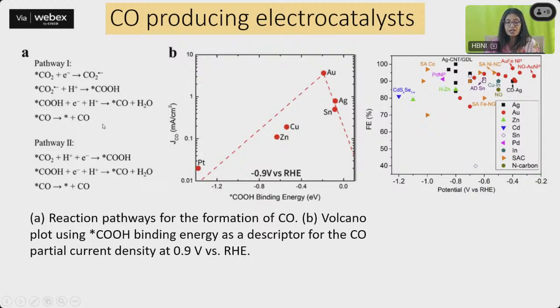Again over here, if you see the process, you are having the metal surface and you are seeing the COOH binding energy, which is again plotted versus the partial current density. And what you see over here is that gold and silver, here not tin, but gold and silver definitely are right at the top in the volcano plot. So you will look into more and more gold-based catalysts. If you see over here, these different kinds of gold-based catalysts are giving a large Faradaic efficiency for the reduction of carbon dioxide to carbon monoxide using electrolysis.